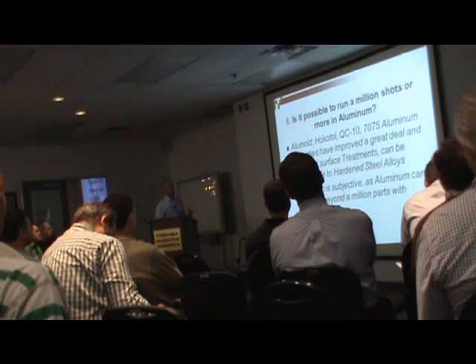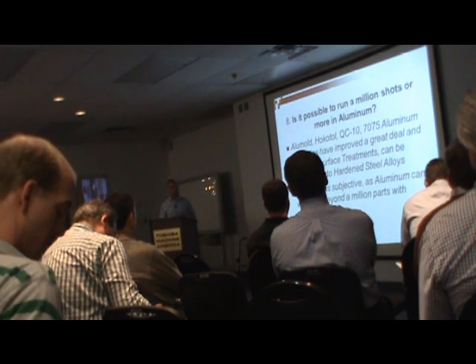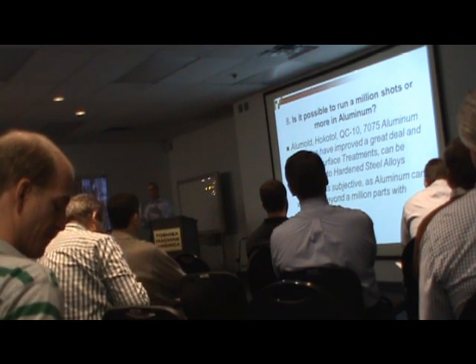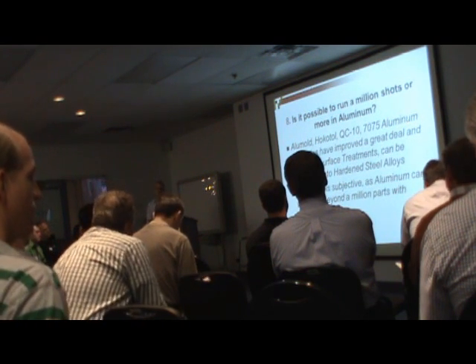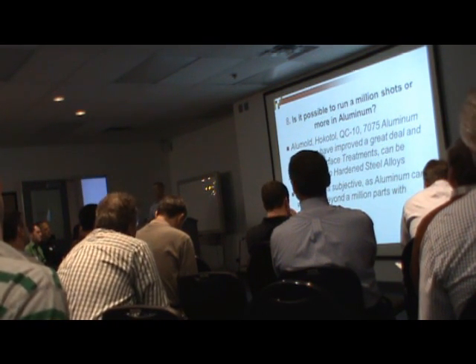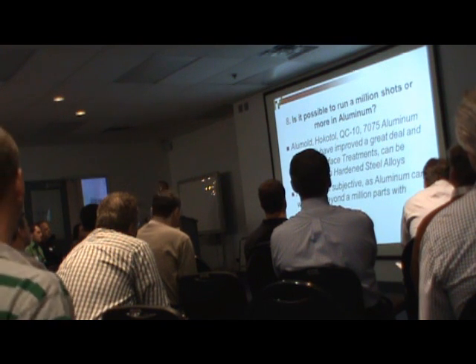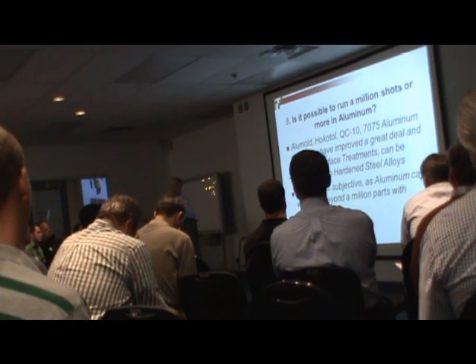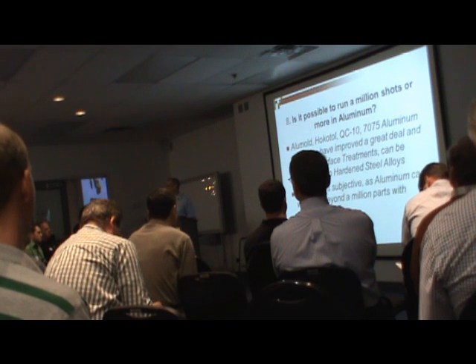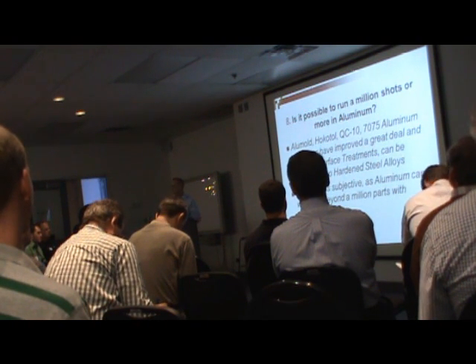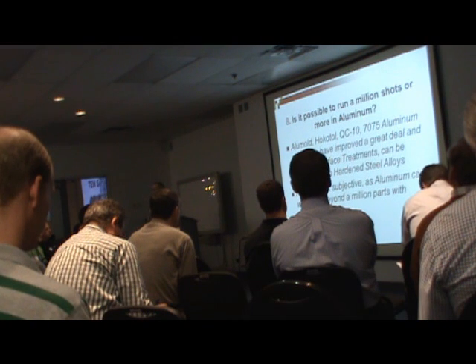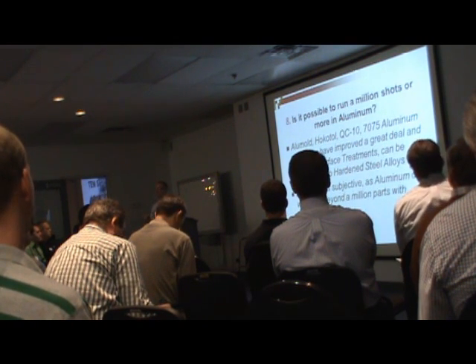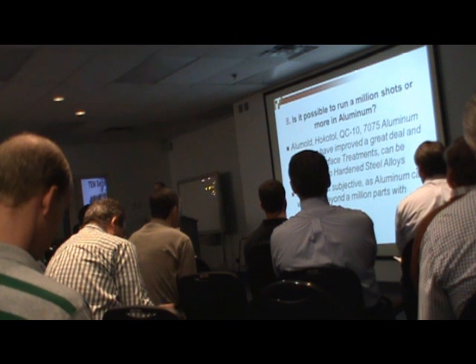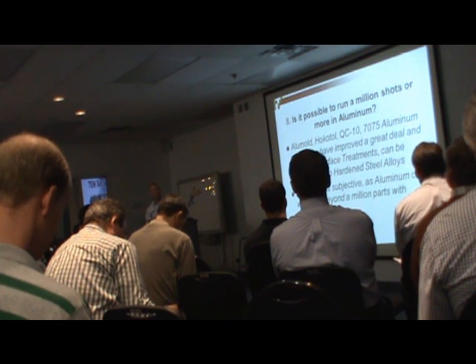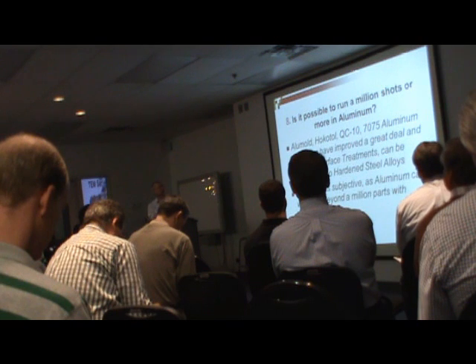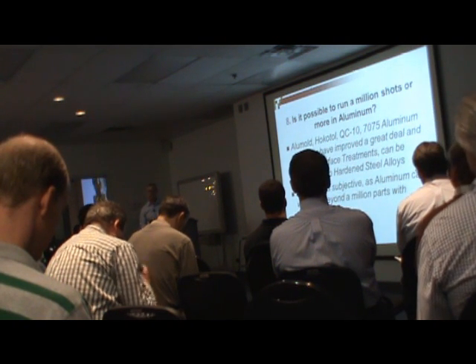Is it possible to run 1 million shots or more in aluminum? Of course, a lot of these grades of material, some you have heard and some not. Some people say this material is better than others. I'm just going by our experience. Majority of our material that we use is 70-75 because the majority of our volumes support that. If they're higher volumes, we're going to consider using some of the other grades besides 70-75. Not that it can't, because I've run over 1 million shots in a 70-75 material, but it was also hard coated. But you have options here of other materials, your Hokotol, your Alumold, your QC-10s, and these are good materials.